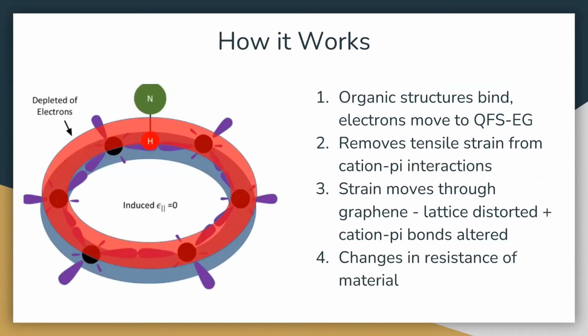And how exactly does this biosensor work? After certain organic structures like the crosslinker or the antibody, et cetera, bind to the structure, electrons move to the quasi-freestanding epitaxial graphene. This serves to remove tensile strain from the cation pi interactions present on the surface due to the crosslinker binding. The strain then moves through the graphene, distorting the lattice and altering the cation pi bonds. This then results in certain changes in resistance of the graphene that we can actually track.